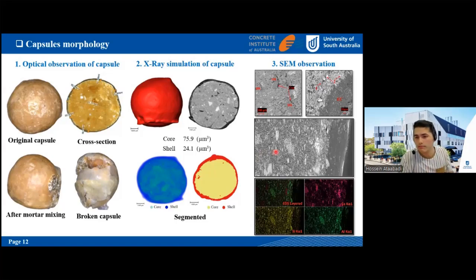We also did some SEM analysis. So if you see here on the right side, this area is the shell material, very smooth shell. So it's showing that the structure is really dense, so it can prevent water penetration inside the capsules during the mixing and preparation of cementitious material.